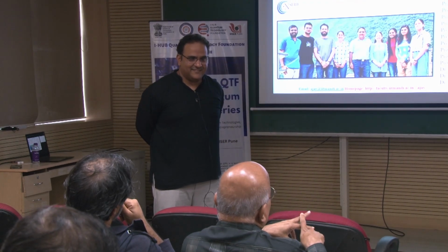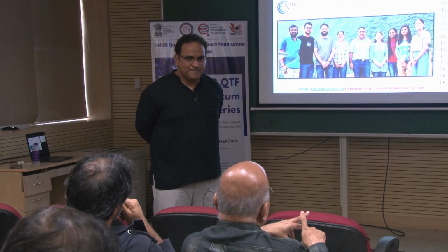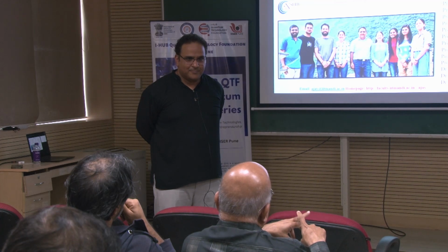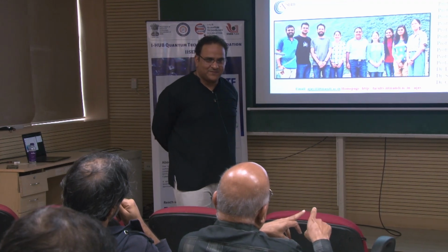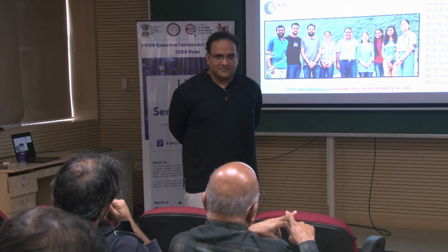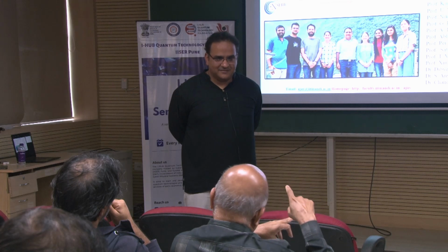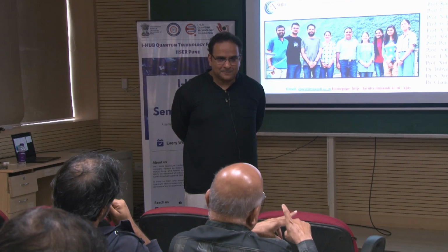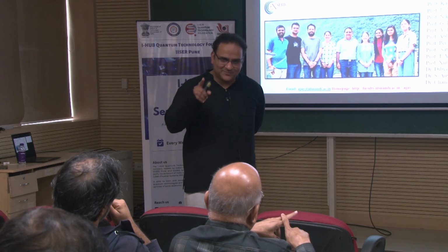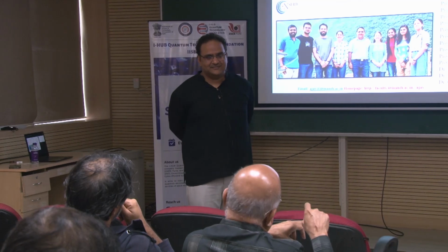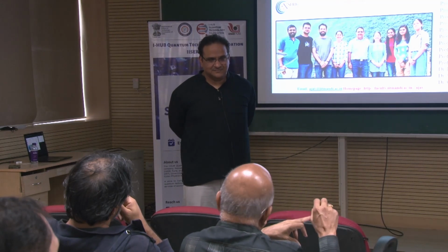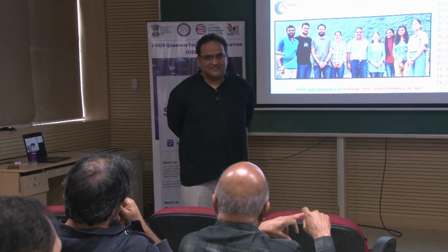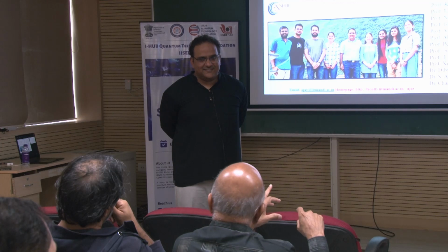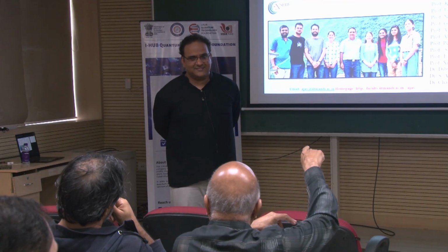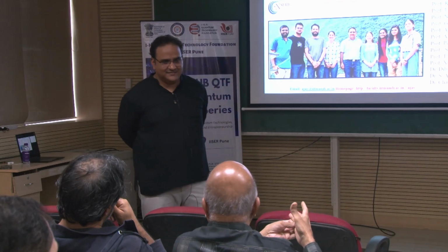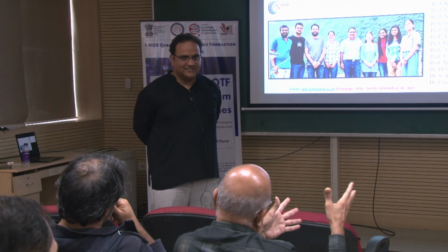The second thing is the CDW increasing with thickness is one aspect. You can take the counter question: if you look at titanium ditelluride, I don't know whether you're familiar with this material, it has the same trigonal structure. This is the only example I know where the bulk doesn't show CDW, but its monolayer shows it. There are very good measurements which show that it is a CDW. Maybe your technique could pick that up, go to the monolayer and see whether these phonon modes, which are enhancing your CDW, may be responsible for bringing out the CDW, because that is an unanswered question in the last decade or so.